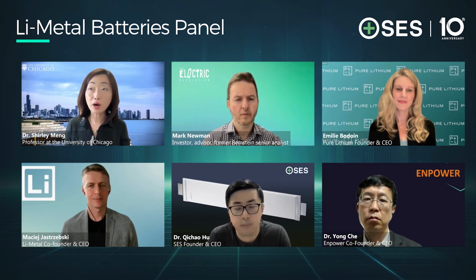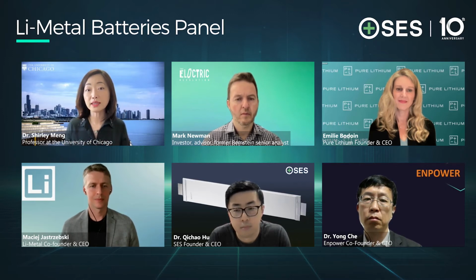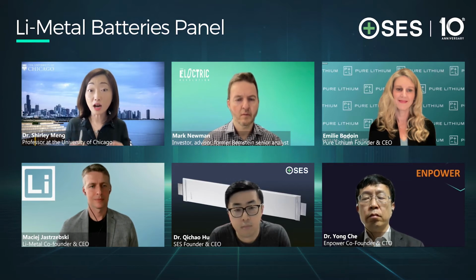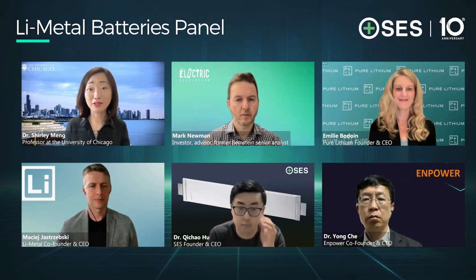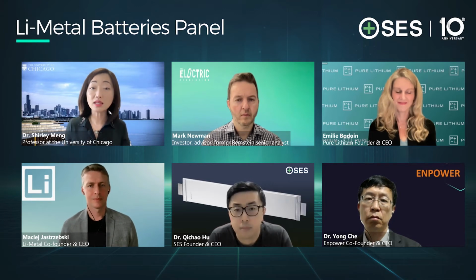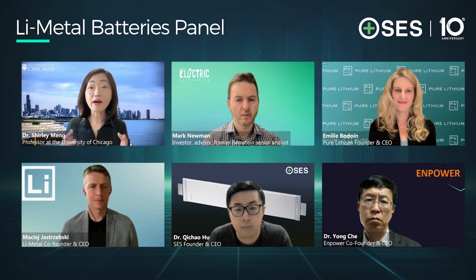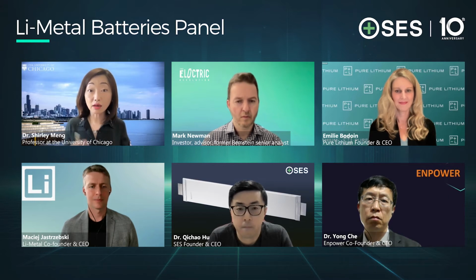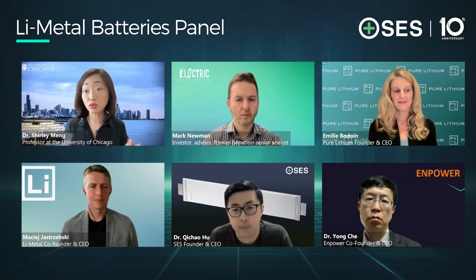The other thing people probably didn't talk too much about, but I know because I did the due diligence report for SES, is the high discharge, high power capability of lithium metal, which we did not see in the silicon anode or even the graphite anode. I think there are special performance metric improvements coming from the lithium metal anode beyond just the energy density number. We all have to take these facts into consideration, and that's the reason why all of us are super excited about lithium metal batteries.